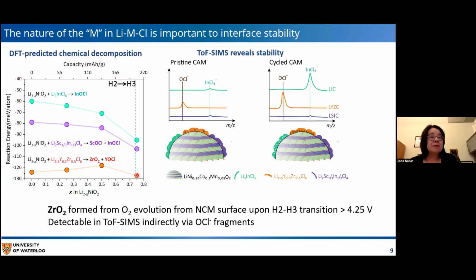And so what we think we form is a passivating layer in the case of the indium, the LIC, and the LISIC, whereas there is a continual formation of insulating zirconium oxide in the case of the lithium yttrium zirconium chloride. And you can see this by comparing the TOF-SIMS results, and these are sort of a cartoon of the data just because it's easier to see.